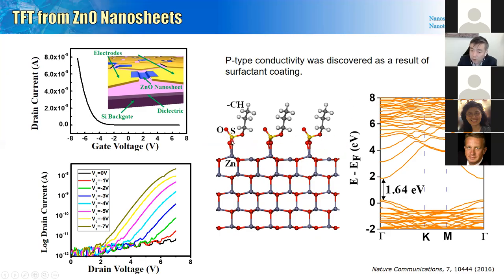The capping of this surfactant monolayer, because of the negative charge it had a group, it'll become an electron draining site to attract an electron from the lattice into this interface to build up at this region because of its charge attraction behavior. So this makes the sheet itself becomes electron deficient. And this makes it, of course, it turned into a p-type conductivity. Right? So this was proved by the DFT calculation to show this Fermi level actually moves down toward the valence band.